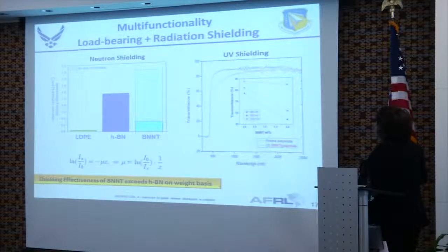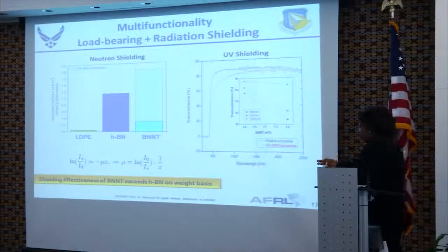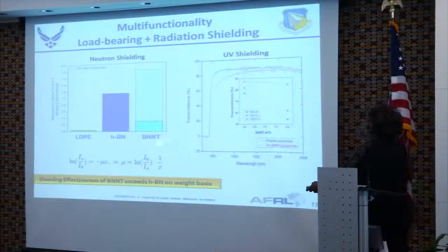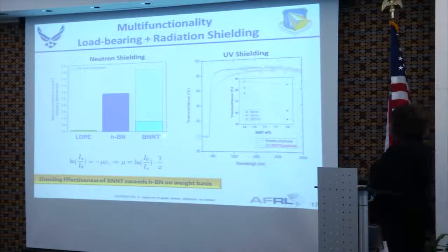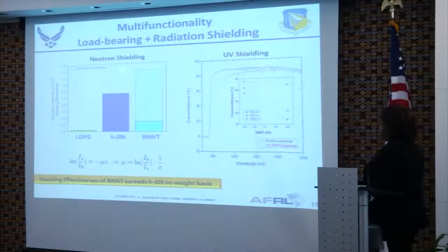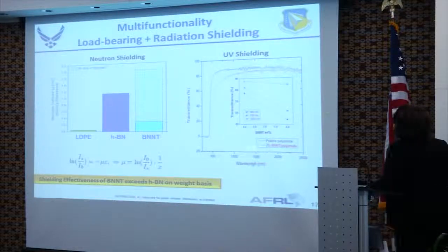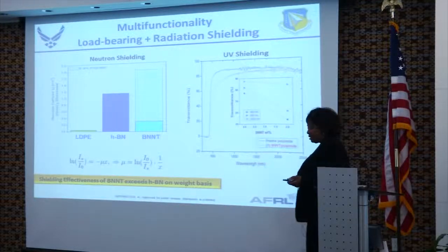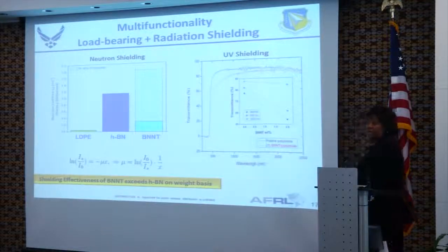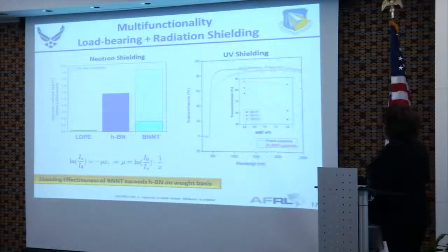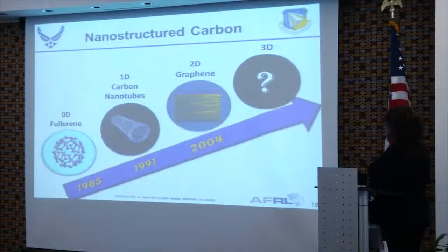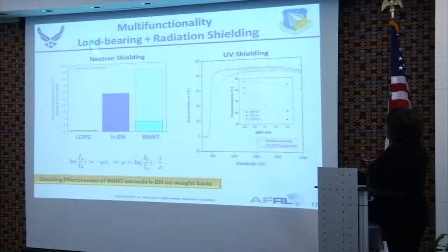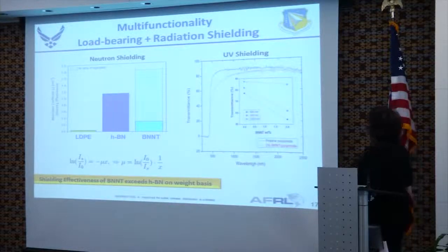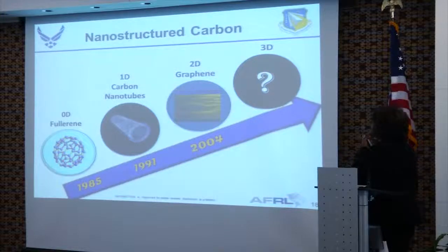But what they found is that because of the good distribution, your ability to really get good coverage and distribution of the boron particles at the nanoscale by using something like a boron nitride nanotube, you have a much greater shielding efficiency with a lower weight or mass of boron nitride. And we, of course, know that boron is used commonly in makeups for UV shielding, and so they've done just some beginning experiments to look at UV shielding capability. So here again, the area is load-bearing plus, and the plus is radiation shielding in this particular case.